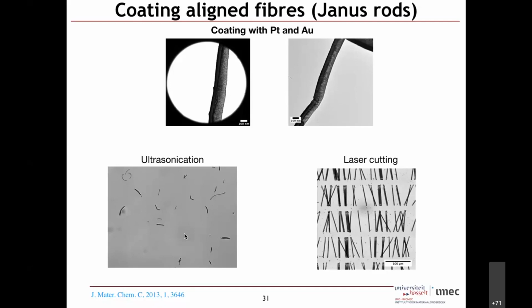If you want to test it, like, can I do it 3 times, 4 times, just to make sure that what you are getting is correct, then you basically cannot use this one. Then we go for laser cutting, where we cut these fibers with a laser and we can get exactly the length. This is approximately 60, 70 micrometers, and that's the length that you're going to get.